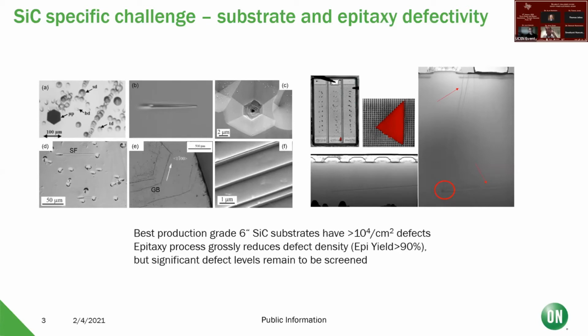Yes, we can produce substrates that we can cut into wafers, and we can handle them with the same machinery and similar processes with modified conditions. But one of the big challenges today is still a lot of substrate defectivity. Good material in this kind of world is 10^4 defects per square centimeter. That compares with probably sub 1 for a silicon device at not only 8 but say 12 inches. We do epitaxy typically for building devices that reduces the defects considerably, but it's still a challenge to minimize that. Next slide.